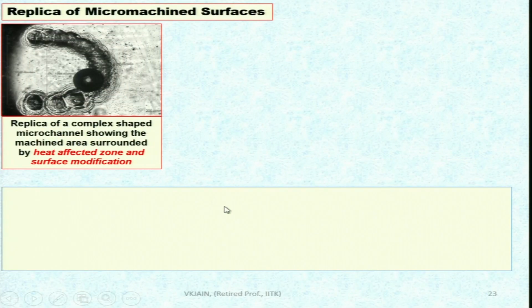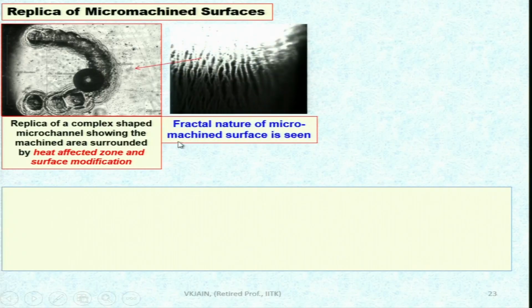Now, this is another one, a micro machined surface: replica of a complex shaped micro channel showing the machined area surrounded by heat affected zone and surface modification. This is the area which has been machined, then the heat affected zone, and some surface has been modified because of thermal effects. Now, if you enlarge this part, you will find that so many micro cracks are there, and such a surface cannot be accepted in real life. So, you have to optimize and do further work, so that you get these complex shapes which are acceptable in real life.